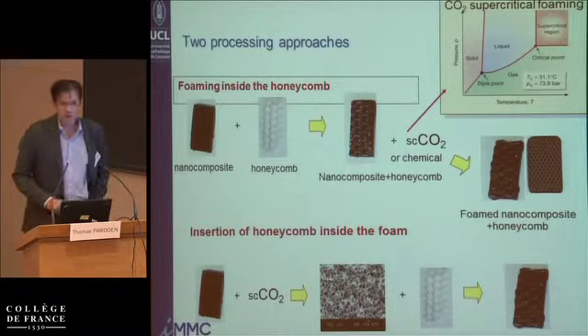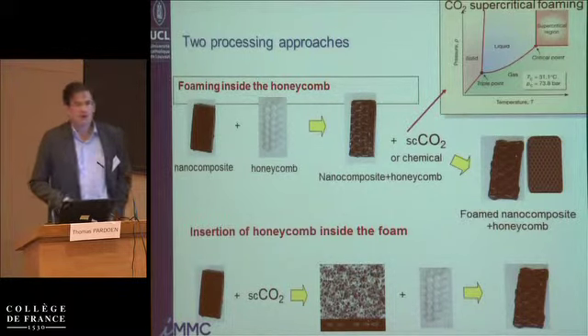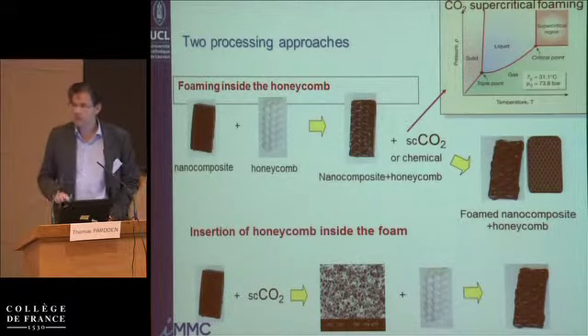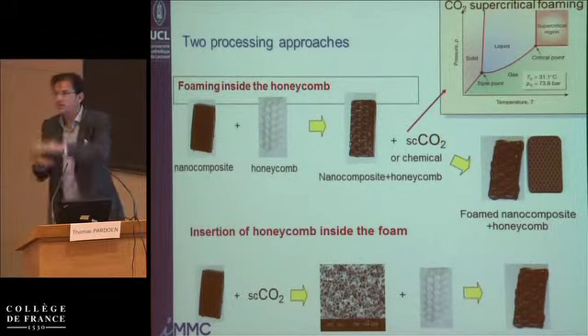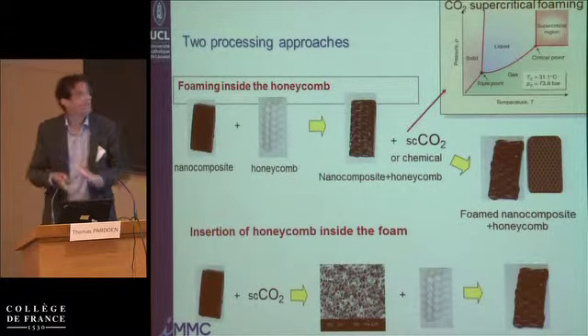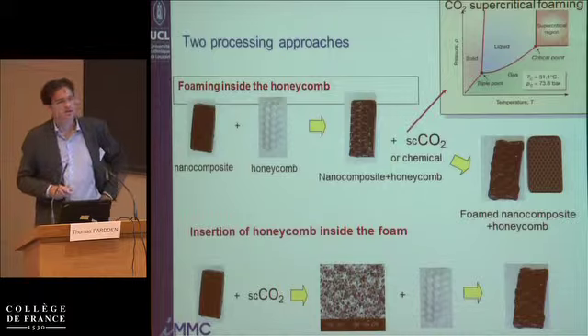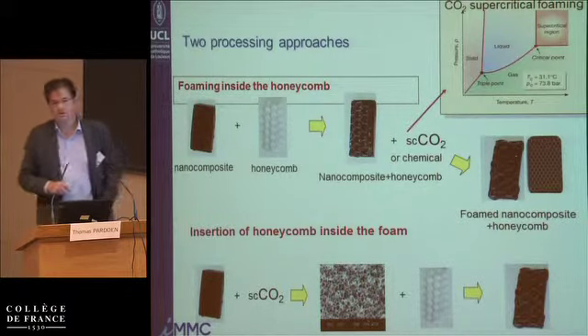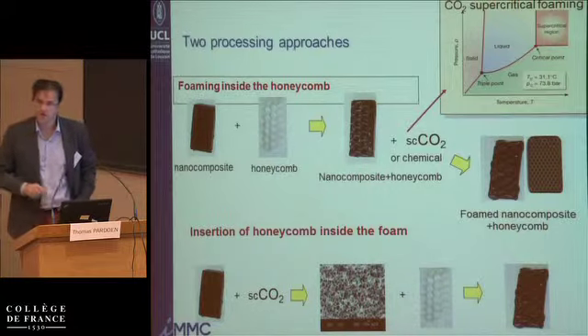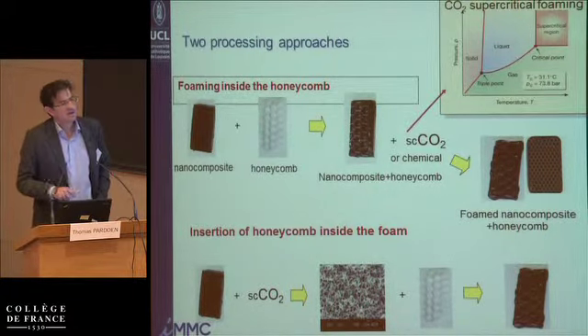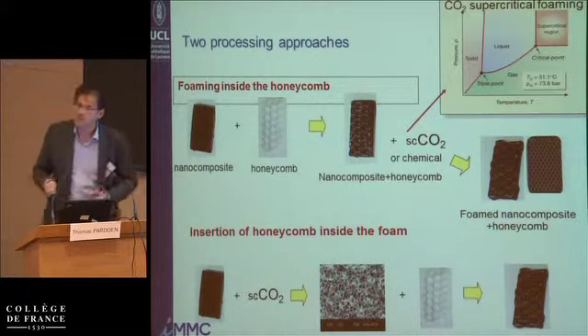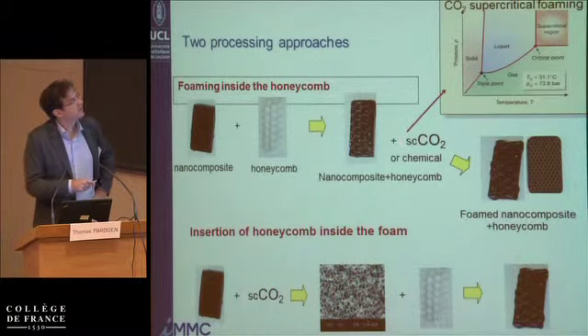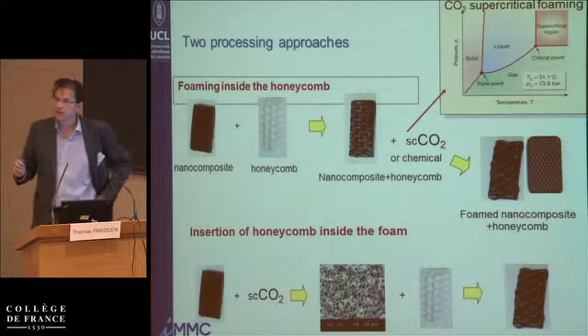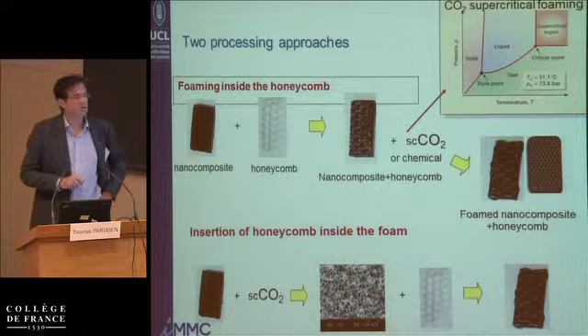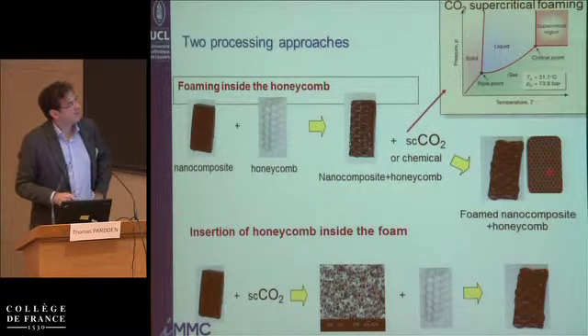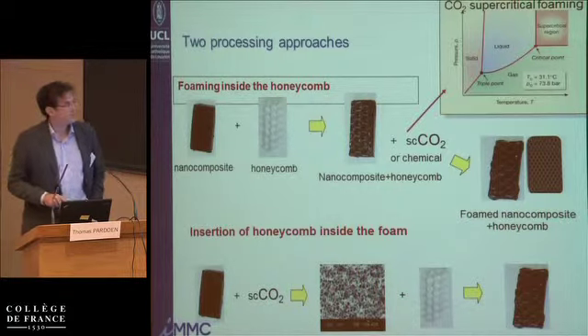It's not that difficult. We have 2 different approaches. You can either make the foam inside the honeycomb, or make the foam and then insert it mechanically inside the honeycomb later on. To form the material directly inside the honeycomb, we use either a supercritical CO2 approach, developed by colleagues at the University of Liège. This gives the best foam, but it's more complicated to play with this technique. Or we can use chemical foaming, but it gives rise to a foam with larger pores, and the mechanical properties of the foam are a bit worse.